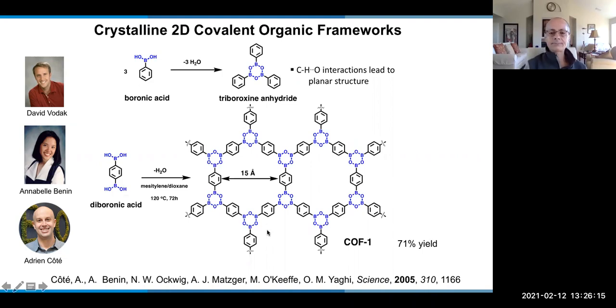hexagonal layer. And so this was our guess, that if you were able to successfully crystallize the result of this reaction, the dehydration reaction, you should be able to make a covalent organic framework. Well, in the beginning, of course, this did not work, because the student who was trying this was an undergrad, Annabelle, and as with everybody else, she was delivering to me X-ray powder diffractions that didn't have diffraction lines. It was all humps. But in the end, we recognized what was going on in the reaction and saw an opportunity to crystallize this material.